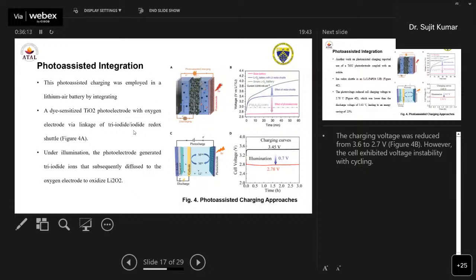So the charging voltage was reduced from 3.6 to 2.7. You can see here from figure B, this is the solar battery, denoted by the pink color. This blue one is the lithium-oxygen, that is the lithium-air battery, with the lithium iodide redox shuttle. You can see the charging voltage has reduced from 3.6 to 2.7. However, the cell exhibited voltage instability with cycling. Due to the illumination, a drop of 0.7 volt, it has reduced to 2.78 volts. So only the charging voltage was reduced, which we have seen from this photo-assisted dye-sensitized titanium oxide.